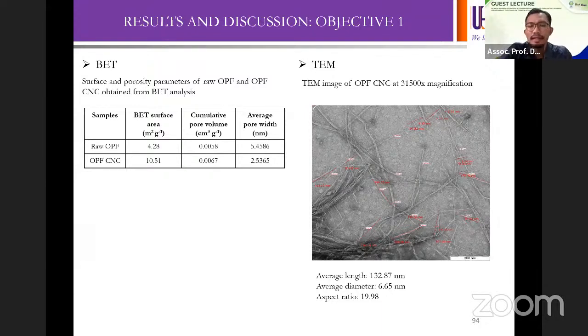And I think the characterization is not complete if we didn't perform transmission electron microscopy. This is very important in order to justify that the samples that we obtain are basically nano in size. Further, we also did BET surface area analysis. And of course, after the acid hydrolysis, we obtained slightly higher BET surface area than before the acid hydrolysis.